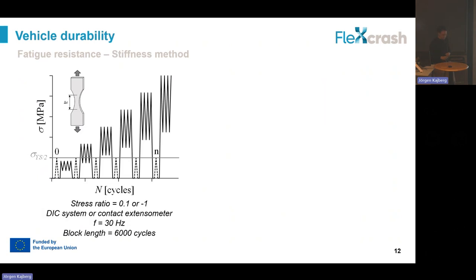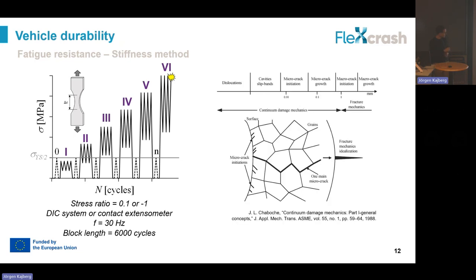And in this case, what we propose, and the main idea in the FlexCrash project, is to use this new test, the stiffness method. In this case, by using only one specimen, we are applying different fatigue blocks with an increasing stress amplitude. And during this test, we are monitoring how the damage is evolving in the material. So we are doing this loading and unloading